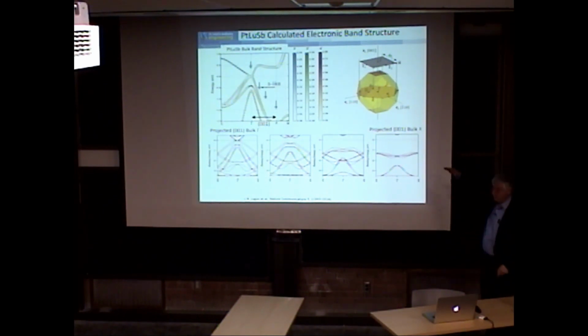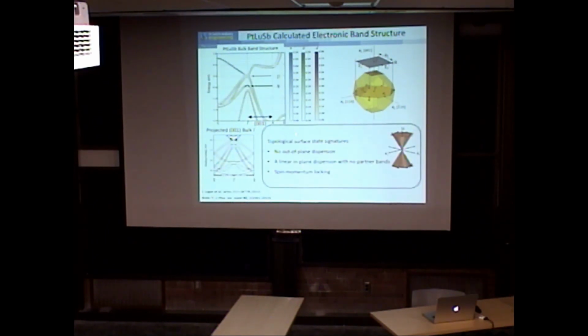So the bulk bands, as I change the photon energy, will go down if I'm looking just in the Z, in the perpendicular direction. The surface state should not change. And we're going to look for this blue surface state, which we've just drawn in there. There's no theory for that surface state except there's supposed to be one there. So what we're looking for, the signature, is there should be no out-of-plane dispersion, to look like a Dirac cone. It should be linear with no partner bands, and we should be able to have spin-momentum locking, meaning there should be a helical spin around these things.